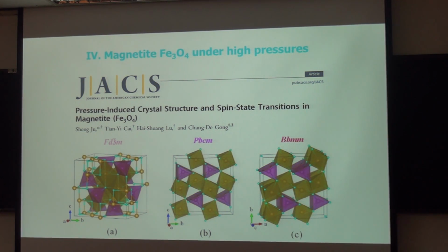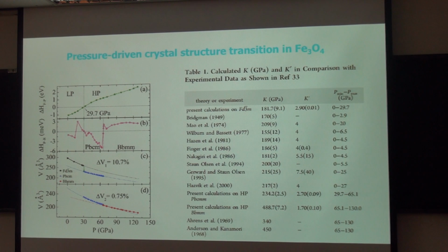However, the experimental observation is very confusing. Scientists still argue in which pressure the system should be in the ground state. So we use first principles methods to determine the exact phase transition or crystal transition in this material. There's no doubt we can find that below around 30 GPa, the inverse spinel structure is the ground state.